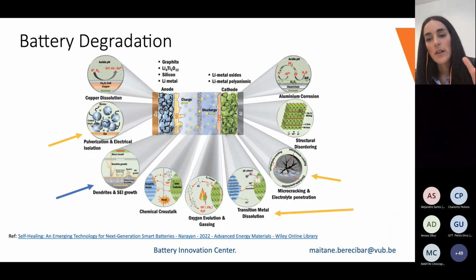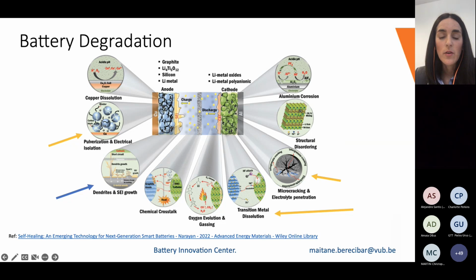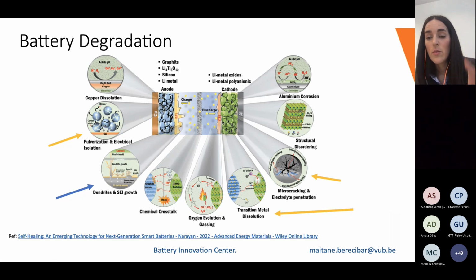If we can see, for example, this is another kind of overview of what can happen in the different parts of the battery, in the anodic side, in the cathodic side. We can see that different degradation can happen: pulverization and electrical isolation, dendrites, solid electrolyte interface growth, transition metal dissolution, microcracking, and electrolyte penetration. And actually, we are already working at the European level on how to stop these degradation mechanisms that can occur in a cell and make them as low as possible.